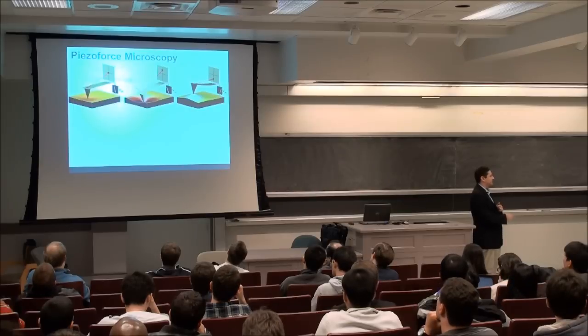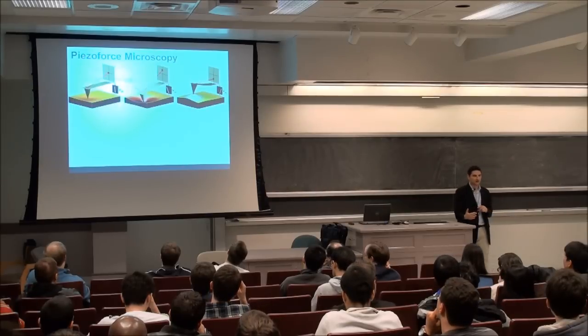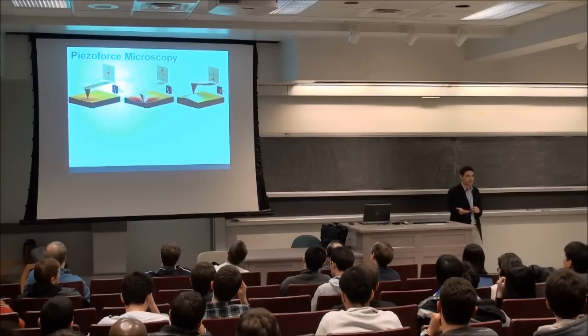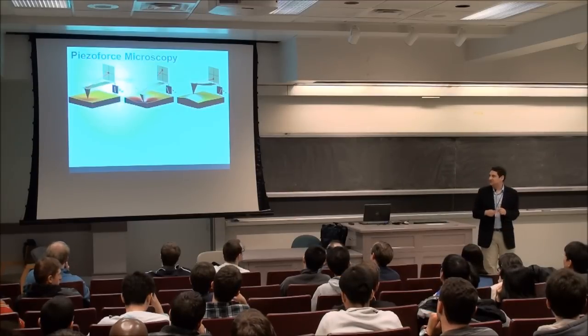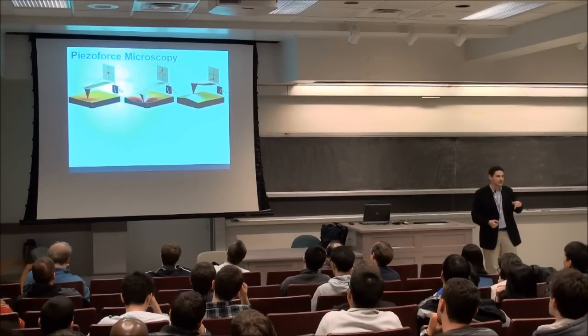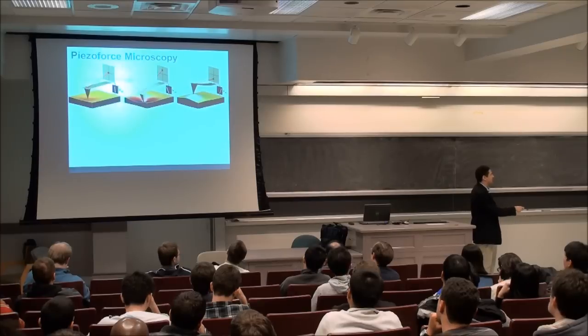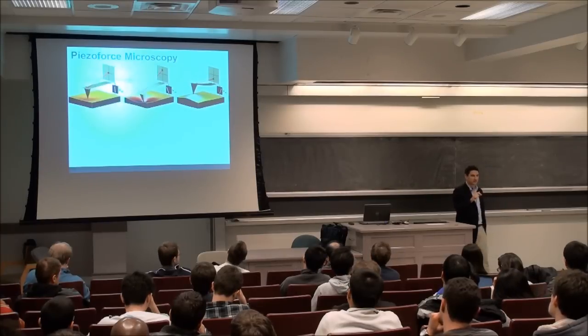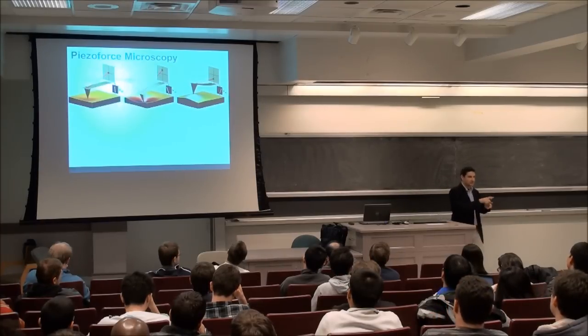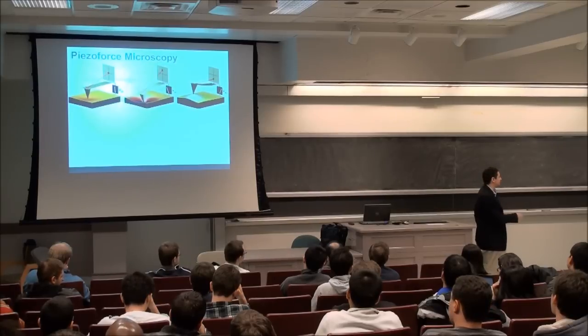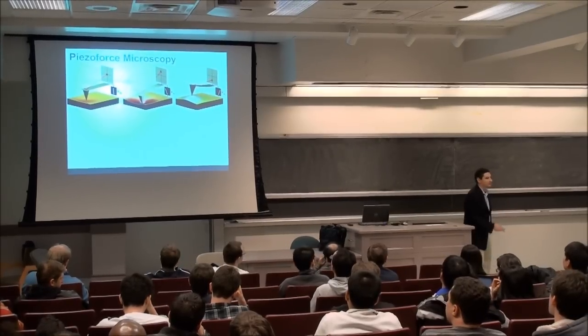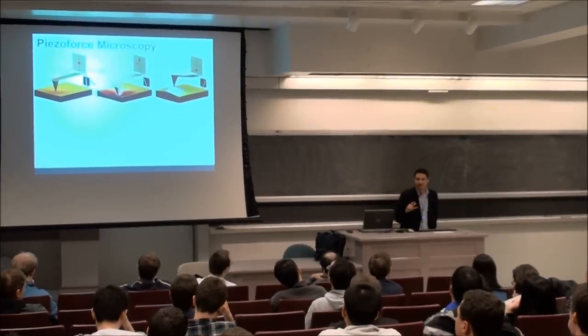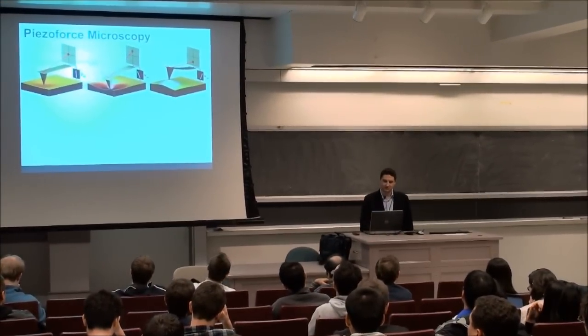And the way that we measured it is this approach called piezo force microscopy, which is just like AFM, which you guys probably know about, but instead the tip is conducting. So you put this conducting tip down on your PZT, you have to have a back electrode, you apply an AC voltage between the tip and the back, and the PZT will basically strain like it's supposed to do. And the ratio between the applied voltage and the strain there actually gives you your D33 value directly.